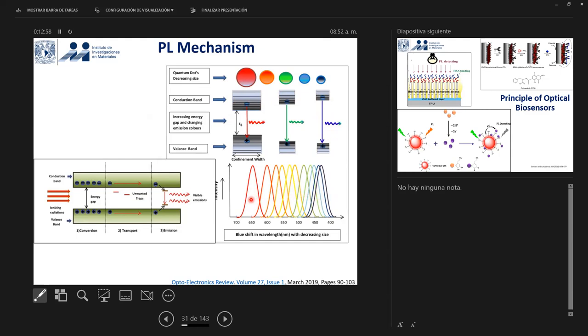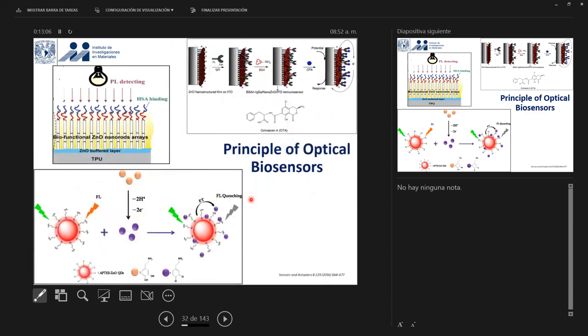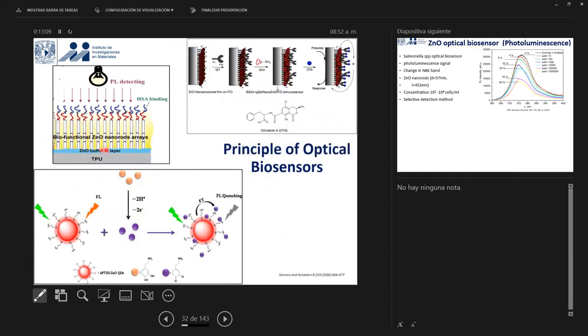And in case of zinc oxide, I'll be showing you some of the important aspects like the luminescence, where it emits, the mechanism behind. But in optical biosensors, the aim is to achieve the luminescence of the pure system like zinc oxide nanowires, nanorods, nanoparticles. And after the binding of analytes, we again detect the photoluminescence. So there are going to be some changes in the luminescence spectra, a shift in the luminescence spectra, or there could be whole quenching of the photoluminescence. The whole photoluminescence could go to zero. That is the main thing we are trying to solve in this case with optical biosensors. And that is the main aim.